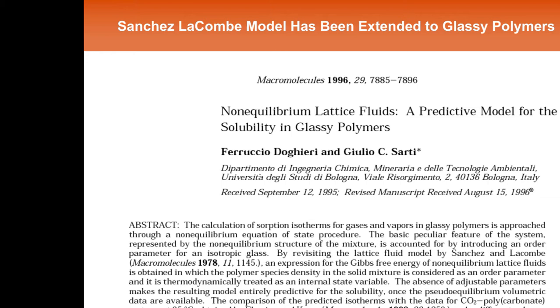And if you stop here in terms of pressure and now start to step down in pressure and measure this gas solubility coming down, the values are not the same as they were going up. Why not? Okay, and so how did that come about? The swelling. The material is swollen a bit due to the CO2 absorption, and as you bring the CO2 back out, that swelling doesn't completely go away, and it leaves the material in a lower density state, and in that lower density state, it is energetically easier to put CO2 molecules in the sample. And so the solubility of CO2 is a function of the history, because the density of the sample is a function of its history.